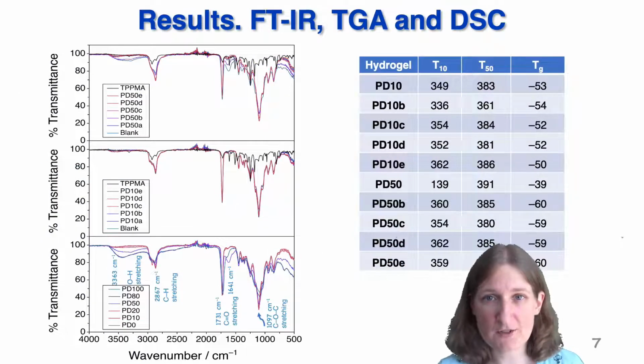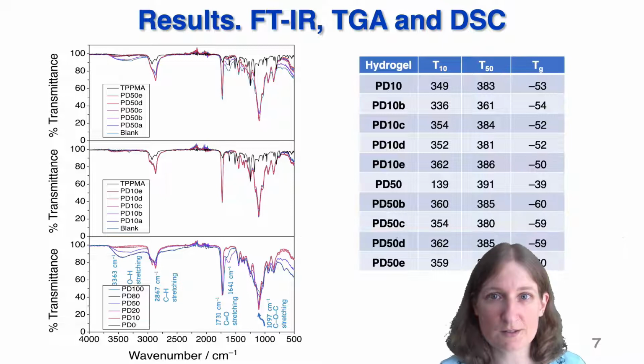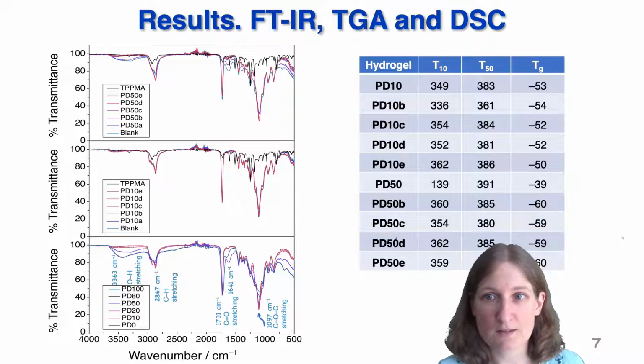The obtained hydrogel series PD50 and PD10 were characterized by FTIR and thermal analysis, TGA and DSC. The composition of both series did not significantly affect the thermal properties and glass transition temperatures. The same was true for the hydrogels with TPPMA present in the polymeric matrix.